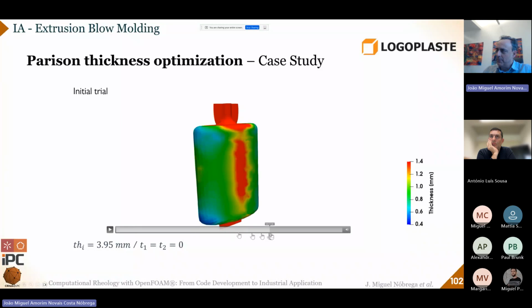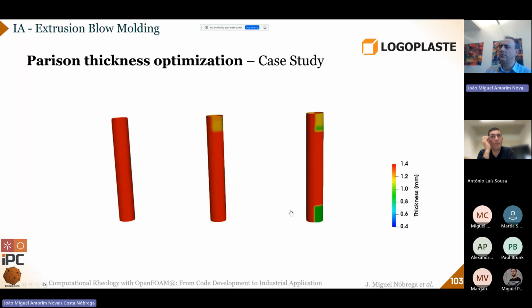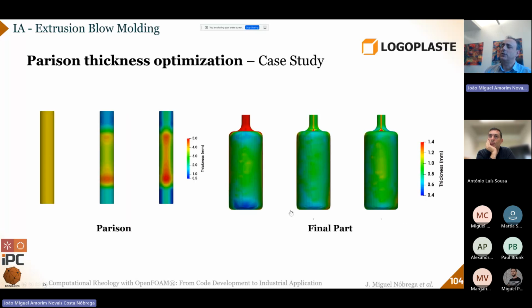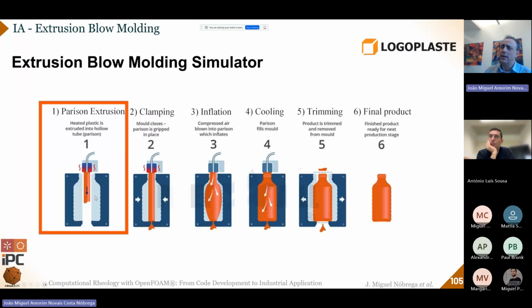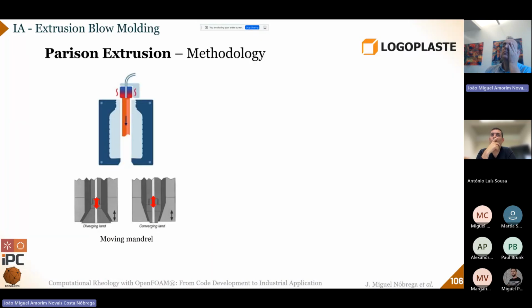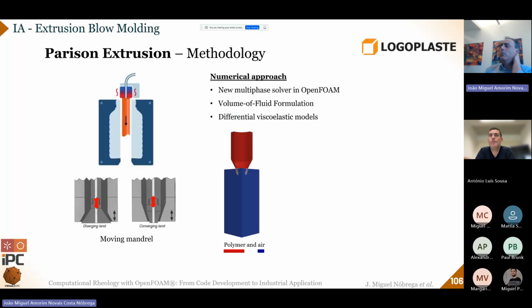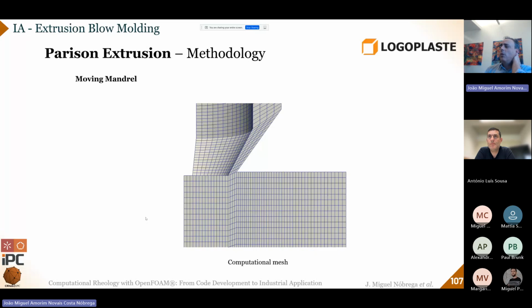I will speed up the movie. You can see in the thickness distribution that there is a reduced thickness near the corners we need to be able to solve. And by doing different iterations, by correcting the process, we're able to obtain the appropriate thickness distribution. We also model the initial part, the extrusion part, by moving the mandrel and adjusting the thickness. And again, we used OpenFOAM solvers and adapted OpenFOAM solvers.